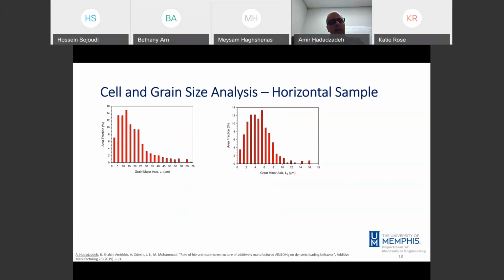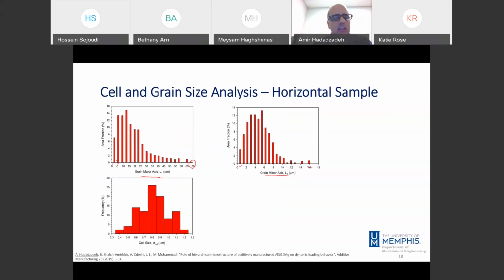study the grains and cells in terms of their size. Since we are dealing with columnar grains, instead of quantifying them in terms of the grain diameter, I quantify them based on their major axis and minor axis. In each columnar grain, I fit an ellipse to the grain and measure the major and minor axis. So the major axis is changing from about 2 micron, as you see on the graph on the left, up to about 17 micron. And the minor axis, this is for the case of the horizontal sample, from about half micron up to 16 micron. And if we quantify the cell structure, we see that the cell size is changing from 0.4 to 1.2 micron.